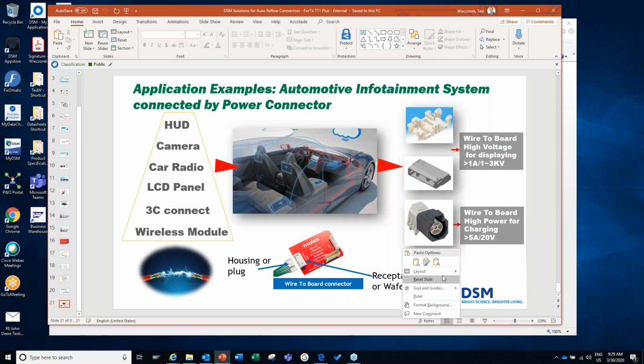Essentially, the T11 material is MSL1. The MSL level is actually rated in parts, so it's not really the material itself necessarily, it's parts made of that material. So in parts made of the T11 material that have wall thickness below 0.8, it is a JEDEC MSL level 1. If you go thicker than that, because the material absorbs moisture into its core, and then the moisture has to come out of that core, then it is only a JEDEC MSL level 2 material.